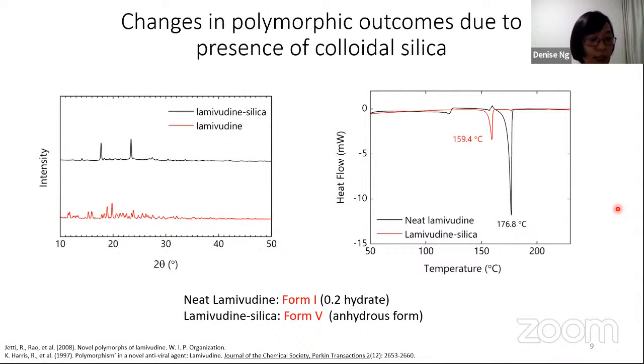Then we also characterize the polymorphic outcomes of lamivudine in such particles via PXRD as well as DSC. In the case of neat lamivudine, we observe form 1, which is a 0.2 hydrate form, whereas in the presence of colloidal silica, we observe form 5, which is an anhydrous form. And this is in line with observations where crystallization under nano confinement in hard templates can lead to the formation of a different form.